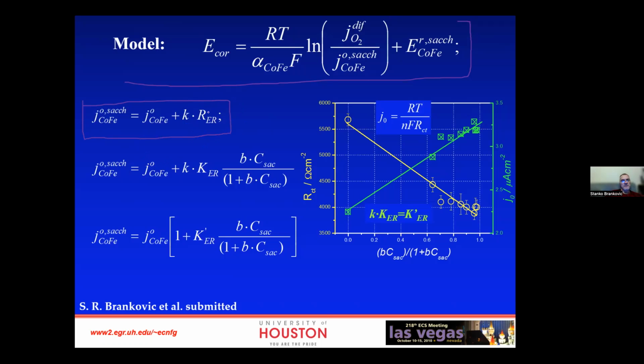Why? Because this term here, as you remember, is proportional to the theta. And so molecule incorporation seems to not affect the corrosion, but only the electroreduction, because we see the linear relation with coverage, not with theta times 1 minus theta. Okay.